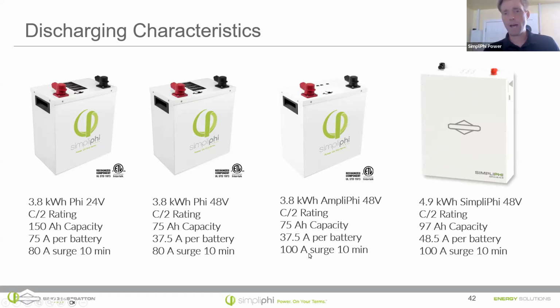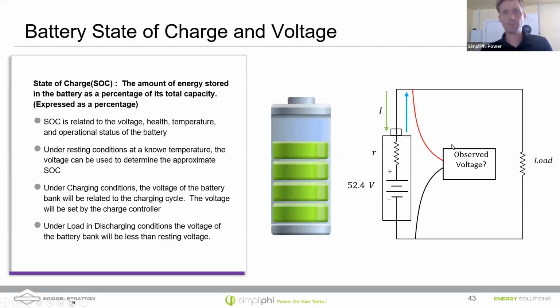That's the maximum this battery will output, but typically this battery will be sitting at 53 volts fully charged. So you can get over 100 amps at 53 volts, which would be over 5 kilowatts of power out of a single battery. You can do that for up to 10 minutes for a real surge there if you need a lot of power for a short amount of time. The SimpliPhi battery can also surge up to 100 amps for 10 minutes. Again, limitations based on the breaker and the BMS there, but that's a huge amount of power out of these batteries for a limited amount of time.